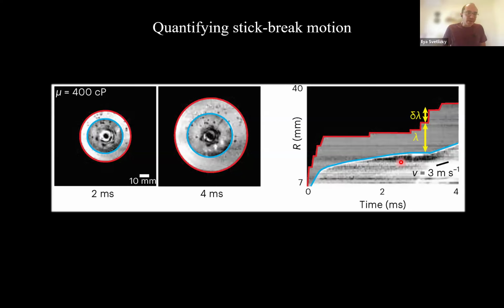So on the left you see two snapshots at 2 and 4 milliseconds. The whole experiment takes about 5. We can track the crack front, this is red. We can track the fluid front, this is blue. And a nice way to visualize the dynamics is to take a single radial direction and plot the intensity along the radial direction versus time. So this is the plot. Again, the red indicates the crack front, the blue is the fluid front.